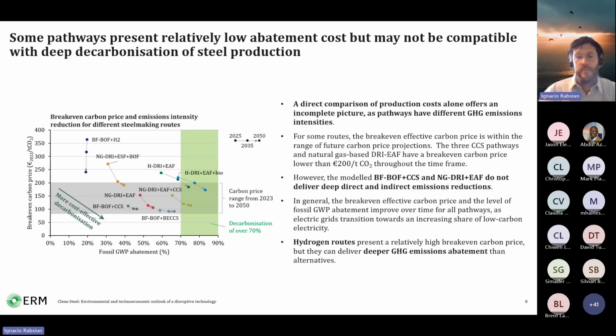We can see that some of the decarbonization pathways, for example, retrofitting a blast furnace with CCS, can already show a relatively attractive break-even carbon price that is roughly in line with expected carbon prices in the EU post 2030, with the effective carbon price. However, they only lead to about 50% GHG emissions reductions, and that may not be sufficient to continue operating in a net zero future. Other pathways like hydrogen direct reduction with electric arc furnace show a higher break-even carbon price, but they allow moving into that deep emissions reduction zone and may make them more attractive from a commercial perspective.